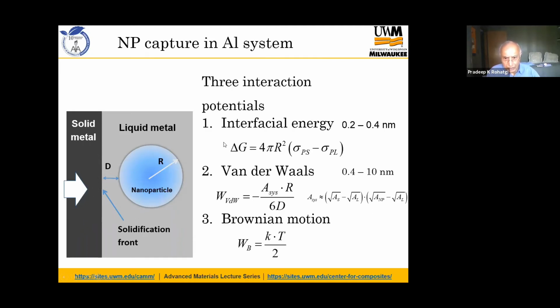And in this case, in addition to the other forces, you also have to deal with the Brownian motion of the particle, and this influences whether the nanoparticle will be engulfed and whether it will be within the grains, because that will influence whether you get high mechanical properties or not.